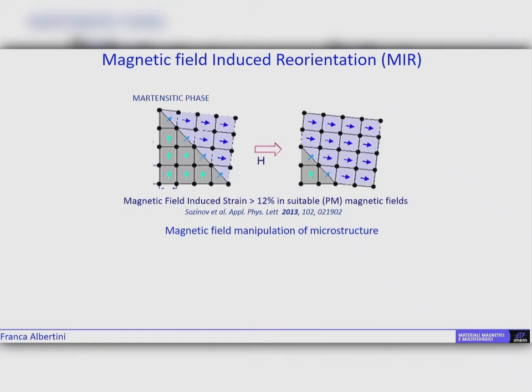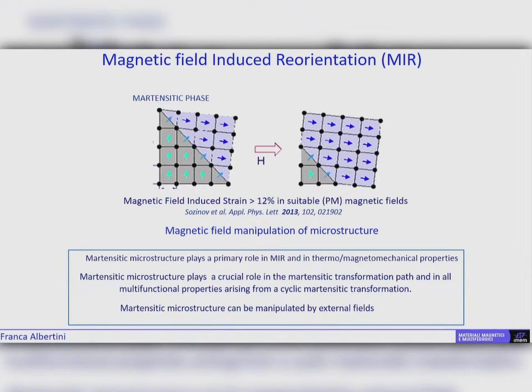Also the magnetic field induced reorientation, that is the property that gives the name to this class of magnetic shape memory materials, is due to the reorientation of twin variants by the application of magnetic field. Here the ingredient is the high magnetocrystalline anisotropy of these materials. And if we have a material, as in this sketch, made of two twins, by applying a field, it's more energetically favorable to move the twin boundary and increase the quantity of material aligned with the field than to reorient the magnetization. So for this reason, we obtain huge strains. And the magnetic field manipulation of microstructure is at the basis of this phenomenon that reaches more than 12% in